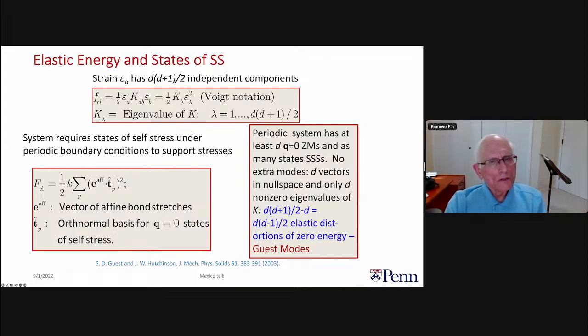So it shows that in order to have a completely stable long wavelength elasticity, I have to make sure that the K constants in K_AB can be diagonalized, and when it's diagonalized, you have eigenvectors epsilon lambda. Since it's in 3 dimensions, we have to have 6 positive constants. So under what circumstances do you not have that? Well, if one of the eigenvalues is 0, then we have a zero mode that goes along with that.